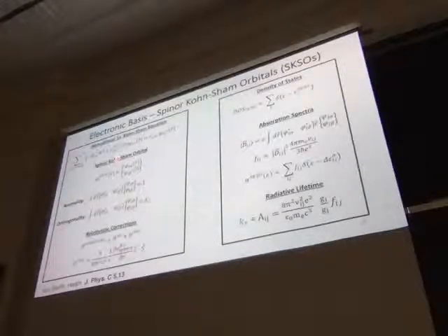The reason we have to use non-collinear orbitals is because in perovskites there is a big relativistic effect due to the lead orbitals that experience large spin-orbit coupling. Within the software that we use, they incorporate relativistic effects, so you have scalar relativistic effects and spin-orbit coupling. Spin-orbit coupling is the big one because for lead, the p orbital has a high angular momentum state. That's what this L represents, the mixing of angular momentum with the intrinsic spin. That's why we have to use spinors, because the spin states are mixed. And this will have important consequences for the electronic states and kinetics in these materials.